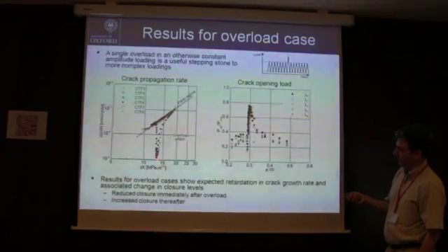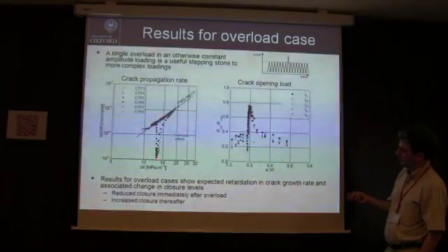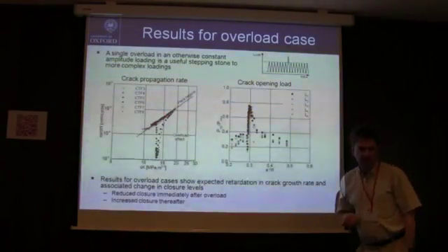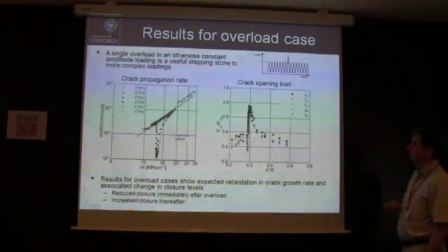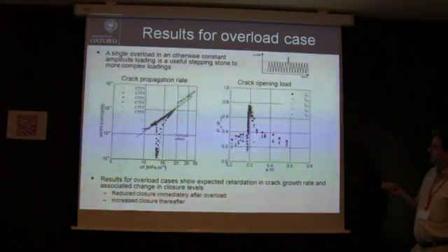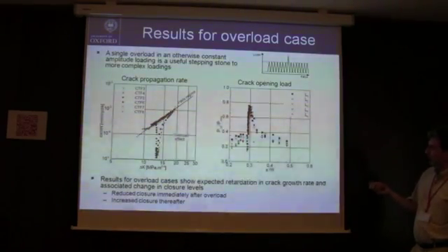It was here. The crack propagation rate drops by certainly 1.5 orders of magnitude, and then it picks up again, but over quite a long distance. So this is longer than the plastic zone caused by the overload. If you measure the crack opening load level, or the crack closure level if you like, here is the steady state value,